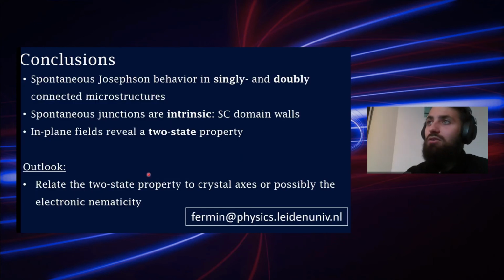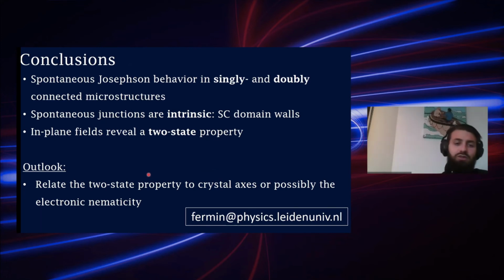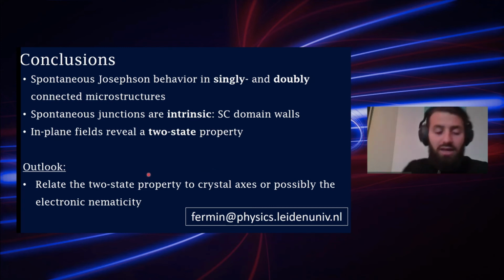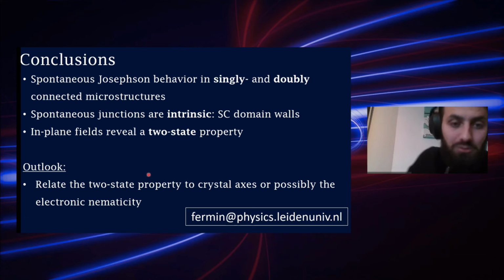Now I will turn to my conclusions. We found this spontaneous Josephson behavior in singly and doubly connected samples, which we interpret as intrinsic superconducting domain walls between two parts of the sample, and probably also between two components of the order parameter. By applying in-plane fields, we reveal a two-state property which we do not fully understand at the moment. As an outlook, we're still trying to relate this two-state property to either the crystal axis or possibly to this electronic nematicity. And with that, I would like to thank you for your attention.